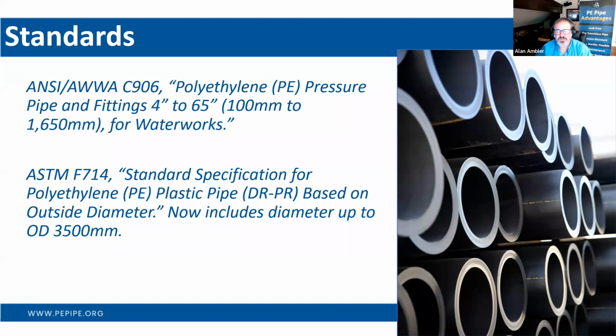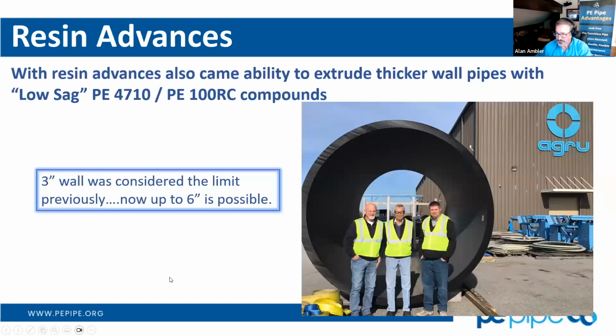And that's one of the things that's really pushed us to standardization of DR11 for potable water, even though it's 200 PSI operating pressure, and most water systems work between 55 and 70 PSI. And then DR17 for sewers, even though DR32.5 would work just fine as a sewer pipe itself in an engineered backfill. So Pete and Mike, if you guys want to come on and talk about some of the resin advances, I think this is where this really takes off.